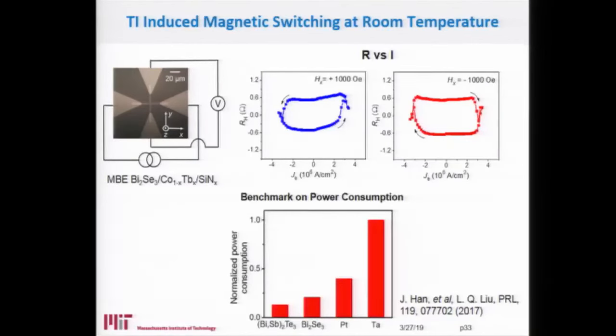Then we pattern the material into this kind of Hall-bar structure, and we can apply current through this bismuth selenide and cobalt-terbium bilayer structure, and at the same time measure the anomalous Hall resistance. As you can see here, when we apply a current in the positive direction, we switch it to the positive Hall resistance. Then when we apply a negative current, we switch it to a negative Hall resistance. So this shows that we can utilize topological insulator to realize magnetic switching in this kind of low moment ferrimagnet.